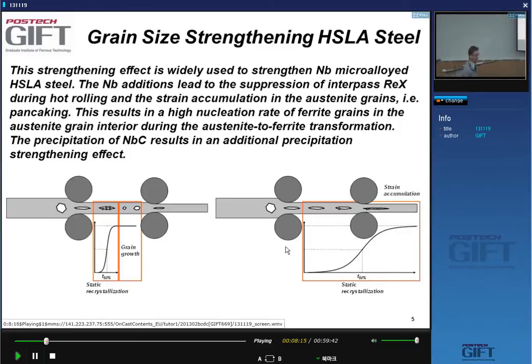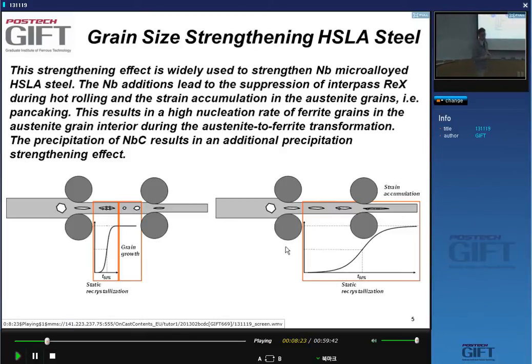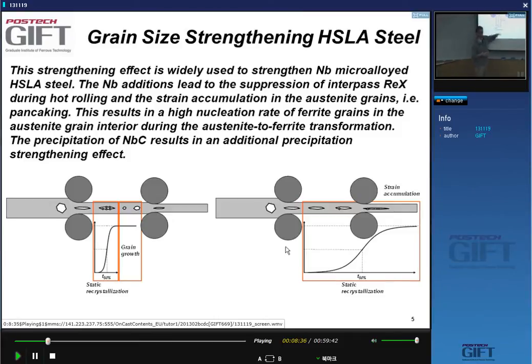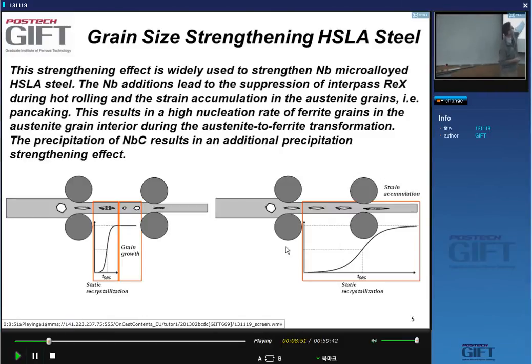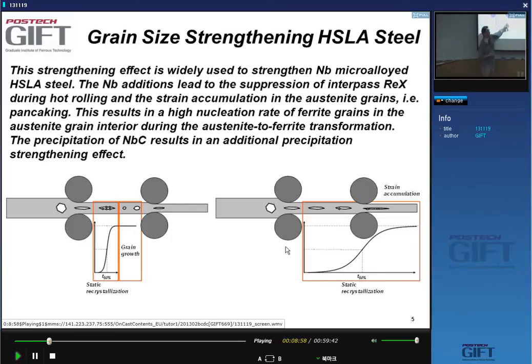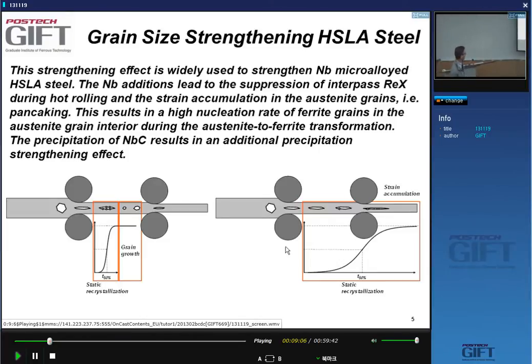A hot rolling mill operates at temperatures so that we deform the material in the austenitic state. When the material gets rolled in one pass, it will instantaneously recrystallize — within less than a second. The static recrystallization kinetics are very fast, and you will actually achieve grain growth before you reach the next deformation in the next roll stand. When you add niobium to this, you get a phenomenon called solute drag, which suppresses the motion of the recrystallization front in the microstructure.